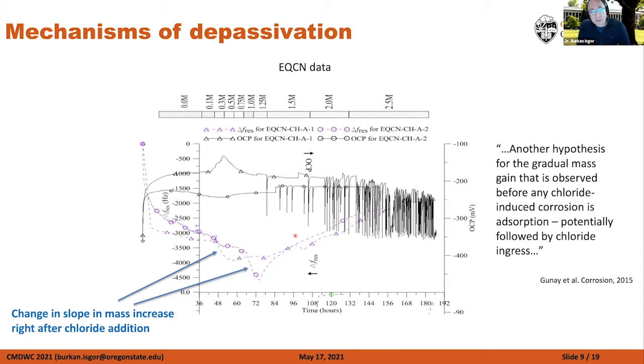Now, this paper was reviewed by three reviewers. One reviewer said that they agreed with us. The second reviewer said that that mass increase probably is due to corrosion product formation. We were able to show that that was not the case, but the third reviewer said that that mass increase is likely because of chloride ingress into the passive film. So you can see even in one paper, in a very simple, over-explained data, there was some controversy. At the end of the day, we were able to make all the reviewers happy by writing this sentence here. Another hypothesis for the gradual mass gain observed is adsorption, possibly followed by chloride ingress. But at the end of the day, I personally was not happy where we were.